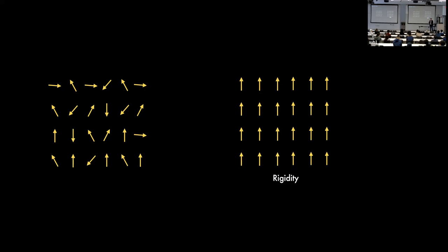It's the same idea, for example, when my voice is traveling through the air to your ears, it's traveling at the speed of sound. But if I was transmitting sound through the floor, or through a crystal, or through this table, it's going to travel much faster because now you have collective motion of all the atoms that are stuck together in the table. So in some words, the speed of sound in this table is a measure of the rigidity of the system. The more rigid the system, the faster the speed of sound. You get similar things in magnets as well. In this case, it's spin that is now rigid. So if I was to inject spin into the system, for example, it would travel much faster across this ferromagnet using the collective motion of all the spins than it would through this gas of spins, which we call a paramagnet.